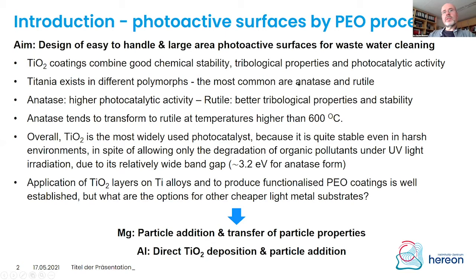the most important ones are the anatase and the rutile phase, where we can basically see that the anatase has higher photocatalytic activity, but the rutile phase is better for tribological properties, and also the chemical stability is better. And what is quite important for the PEO processing is that anatase tends to transform into rutile if the temperatures are actually higher than 600 degrees Celsius.